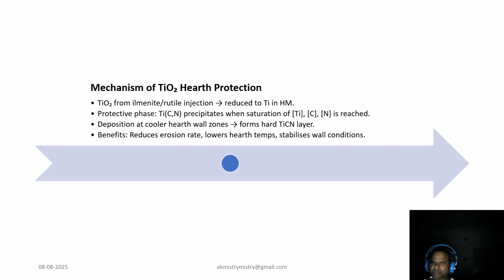When we inject or charge TiO₂, it is partially reduced in the furnace to metallic titanium. In the hearth, hot metal titanium combines with carbon and nitrogen to form titanium carbonitride, that is TiCN. This TiCN precipitates out when the saturation product of Ti, C and N in the hot metal is reached. These crystals migrate to cooler hearth wall areas and form a dense, hard protective layer. That layer acts like a shield, reducing direct contact between molten iron and carbon brick.